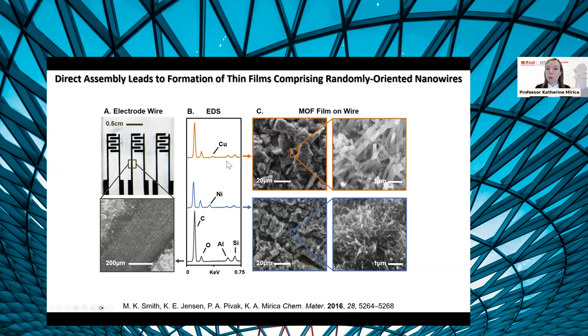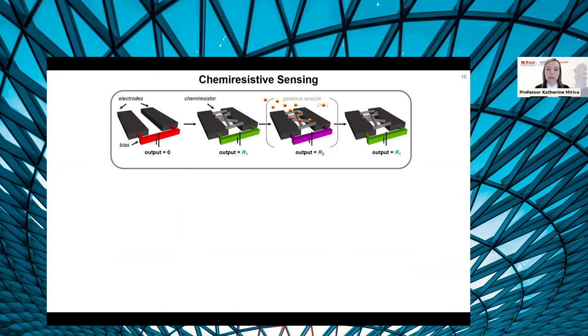And then to probe the function of these devices, we place them into a chemiresistive device architecture. So this is simply just a two-electrode device. In this particular case, these are the interdigitated electrodes that are bridged with the active sensing material. In this case, that's our framework material. So what we do here is simply apply a constant voltage and measure current. And we look at changes of current that result from the exposure of the sensing material to the gaseous analyte.